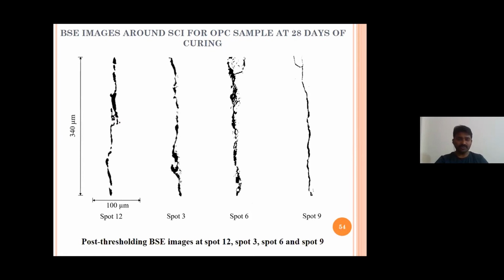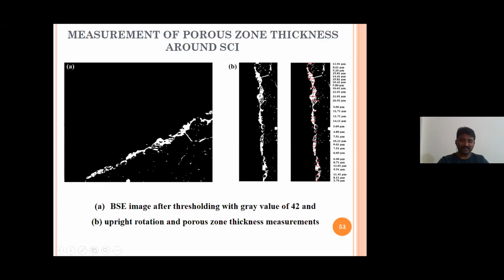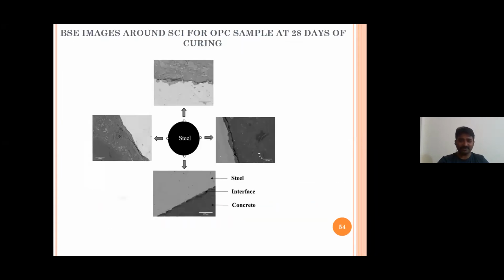So what is the use of identifying this porous zone thickness? Once you get the porous zone thickness, we can identify how much time is required for the corrosion products to fill this much area. Right? Due to time constraints and for analysis purposes only, we have considered 12 locations. But if you increase the number of locations, your accuracy will increase. So why did I end up with only 12?